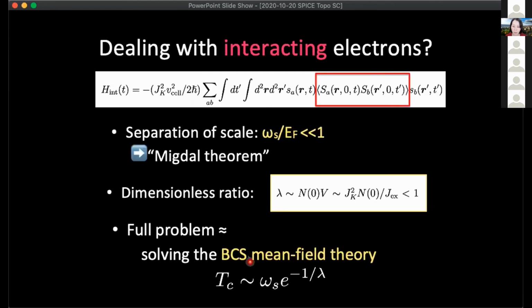And when we studied this a little more carefully, we confirmed all this sort of qualitative intuition-based thinking, and we could proceed as if we're studying an electron-phonon system, and you get the pairing, the superconducting TC, in a form that looks familiar, except that now this is not the phonon frequency, this is the spin energy scale, and this lambda is the dimensionless pairing strength.